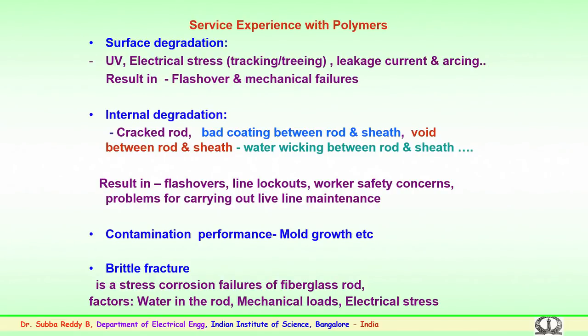So, there is contamination due to mold growth also. And as mentioned above, the brittle fracture, again I am stressing this. This happens due to a combination of reasons, like the crimping issue in the fiberglass rod during the manufacturing stage, or during operation where the corona control rings are not properly designed or not properly placed. The discharges coming out from the corona control rings continuously hit the surface of the polymer insulator, further damaging the insulation.